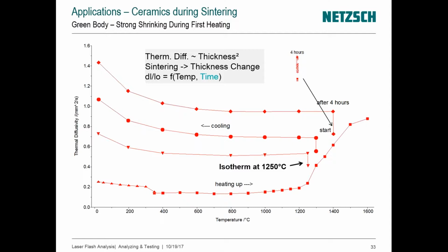In a way, as what we would obtain heating up, if you go back to the square marks, what we would obtain with the square marks at the end after the sintering at above 1,400 degrees tend to be the same range as what would be obtained if we maintain an isotherm for 4 hours at 1,250 degrees C. Basically, the range of conductivity, diffusivity will be much higher. And then as we cool down again, we see that the diffusivity will increase as the temperature is lower, essentially. But the point here is that it's a way for you to monitor, or to see, that the temperature at which the sintering will occur is also important.